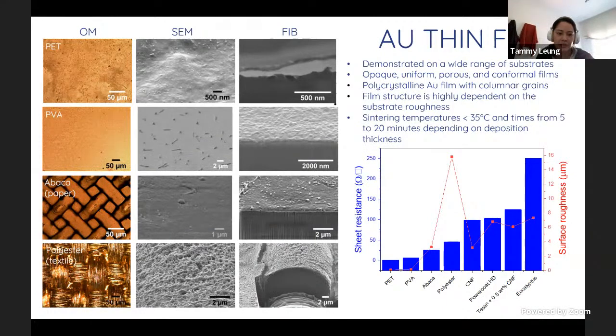We see that specifically through the deposition onto non-planar substrates such as abaca paper and polyester textile, the film was formed extremely conformally, which is something that has never been seen before. These films, again, were sintered at 35 degrees C or below, which makes it a low temperature process itself.